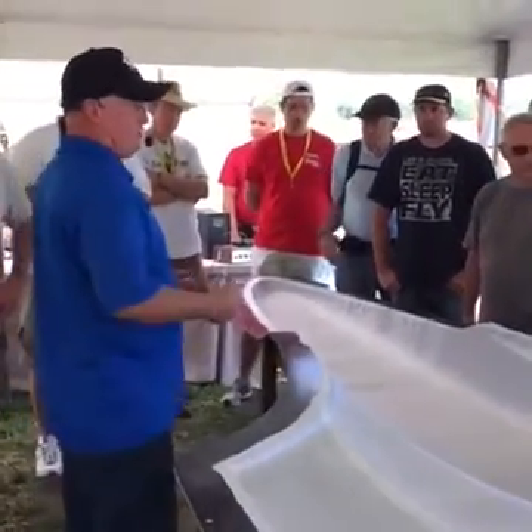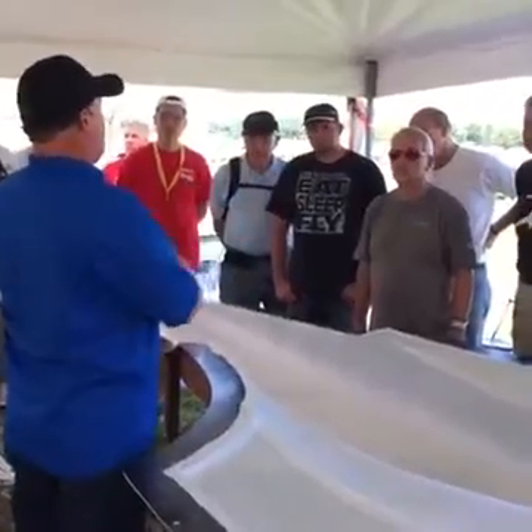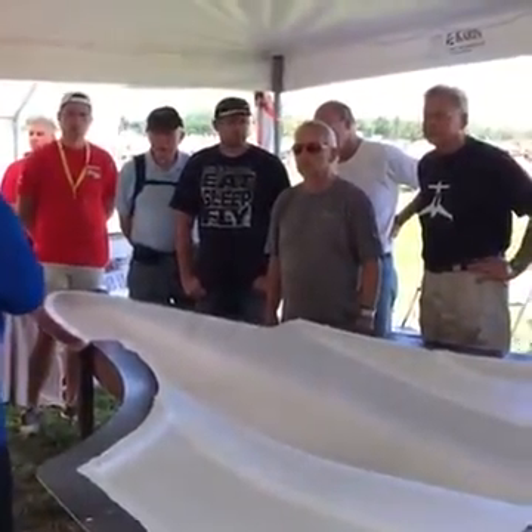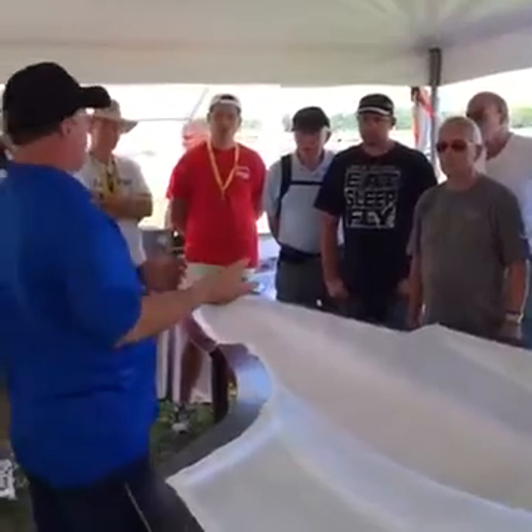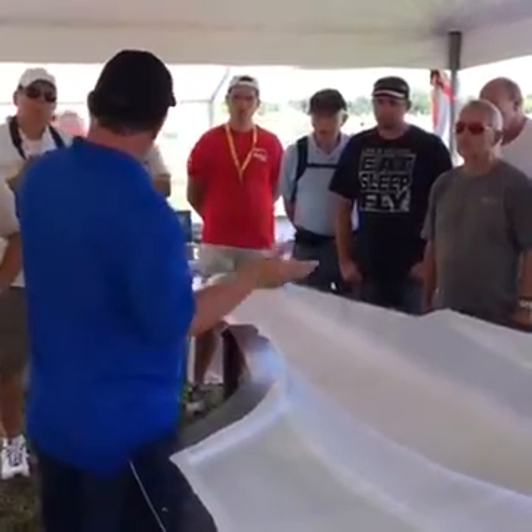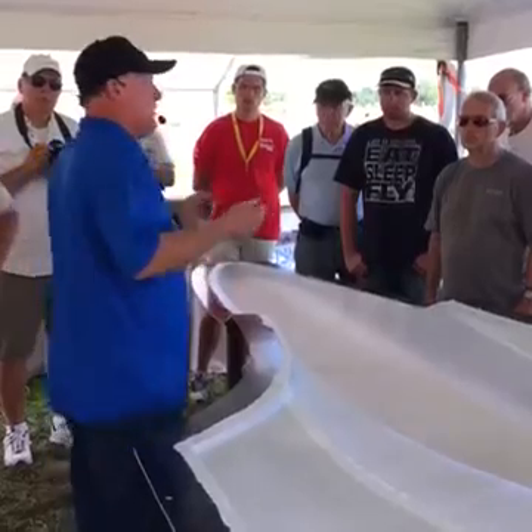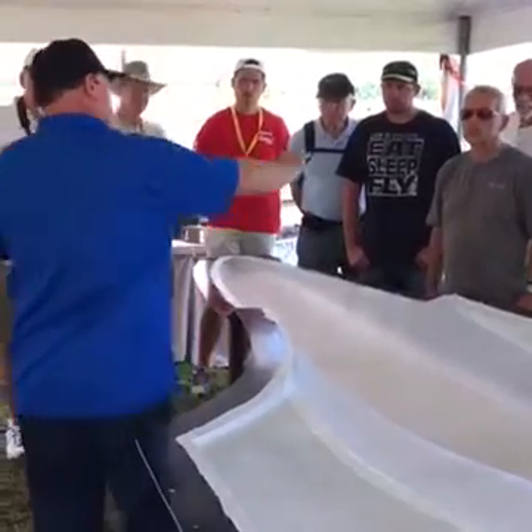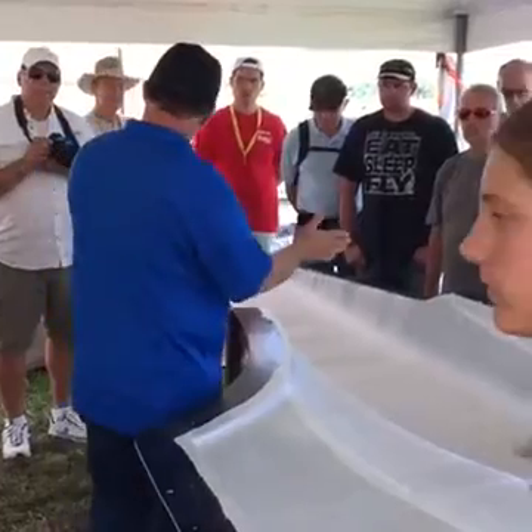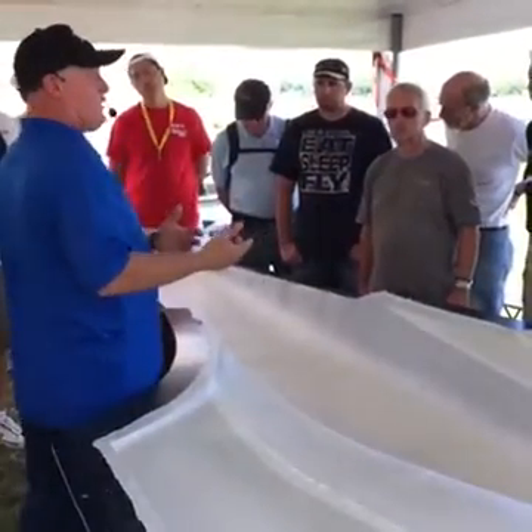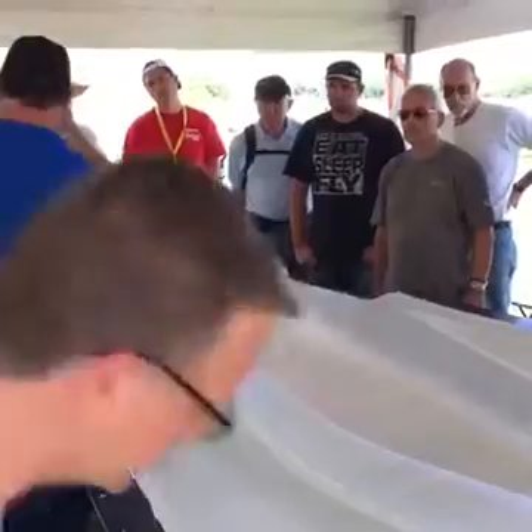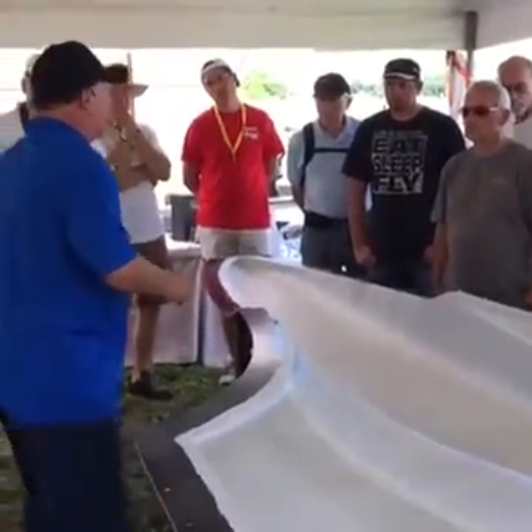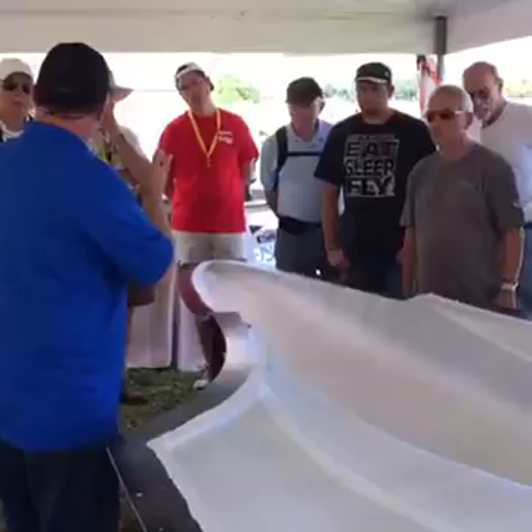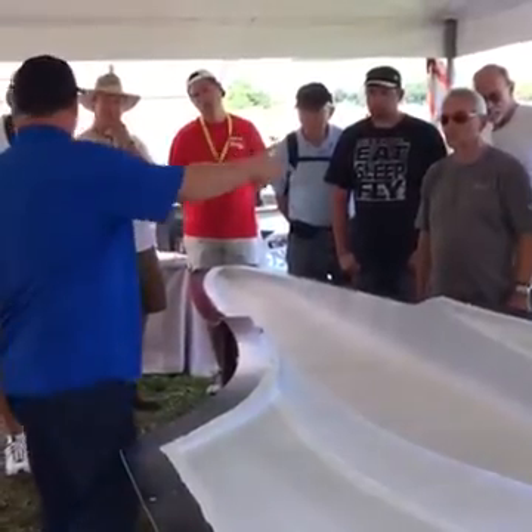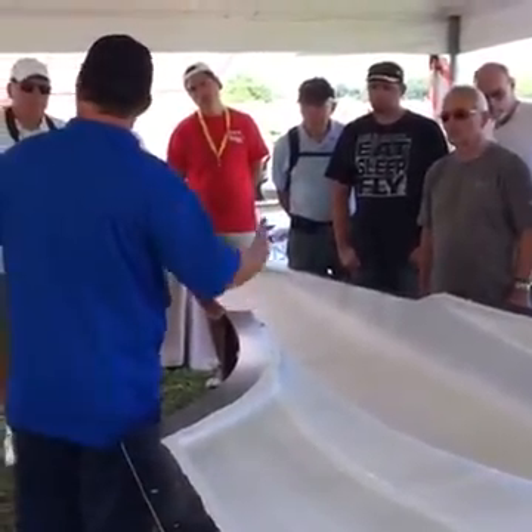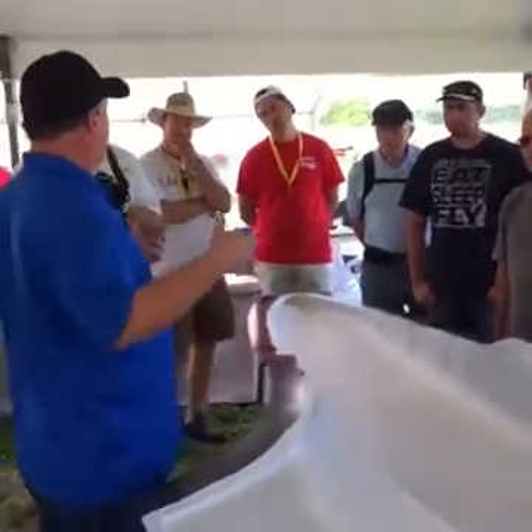So infusion allows you to create parts, even standalone, like a wing. You could actually infuse that skin and use the bag as the mold surface. As long as you keep that bag nice and taut and smooth, once it's infused, even using low pressure, you come back with soapy water on the back side of that bag and squeegee it so that you get a really silky smooth finish across the part. So a hand laid part can become less work in trying to get it finished and prepped for the primer.